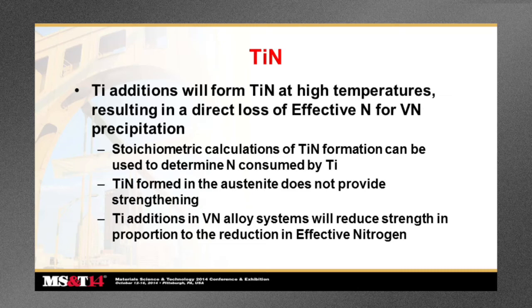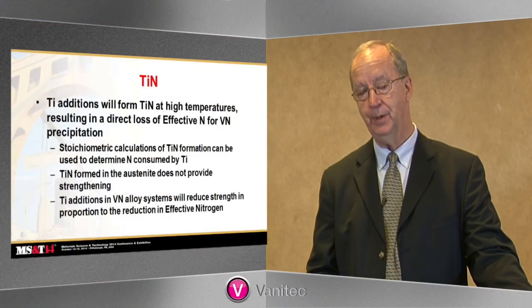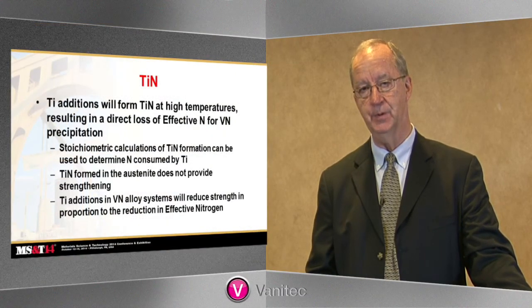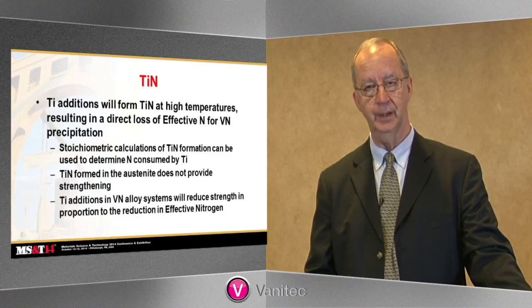Virtually all of the titanium nitride forms in the austenite. It tends to be very coarse. It is not a strengthening size precipitate. Therefore, the titanium additions in a vanadium nitrogen system actually reduce the strength in proportion to the amount of effective nitrogen removed. They can possibly be an effective high temperature grain growth controlling precipitate, but they do not contribute to strength after the fact.